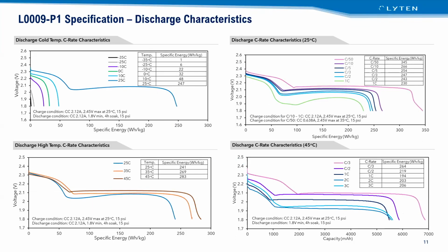The other thing about this chemistry is that it is a conversion chemistry. It is driven by these chemical reactions. So what happens is when you raise the temperature, you get more capacity and you get better rate capability and everything else. Where this cell would do about 250 watt hours per kilo at C/3, if I go real slow on it and maybe raise the temperature a little bit, I get close to 350 watt hours per kilo. You can see this here too at different temperatures. I'm going from a cell at 25 C, this 250, 240, to about 280 in capacity. So that's kind of a nice bonus. You don't see that much. You want to run it hot.